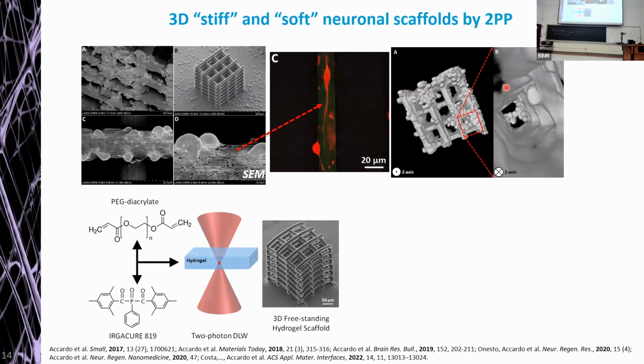And I combined it with a photoinitiator called Irgacure 819, which allows the triggering of the 2-photon absorption phenomenon required to perform 2-photon polymerization. In this way, I was able to obtain woodpile structures with a feature resolution very close to the one of the optimal IP-Dip, that is the name of this material here, optimal IP-Dip 2-photon polymerized material. The difference here is that PEGDA has a Young's modulus which is in the range of hundreds of kilopascal. It's way lower than IP-Dip.